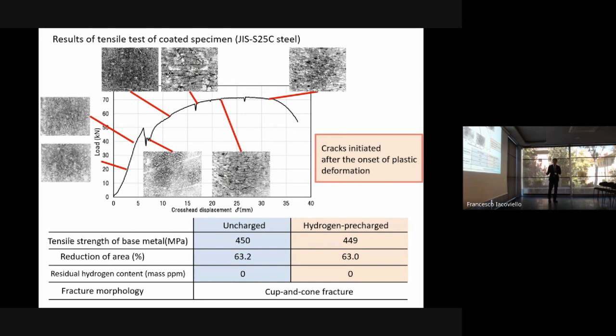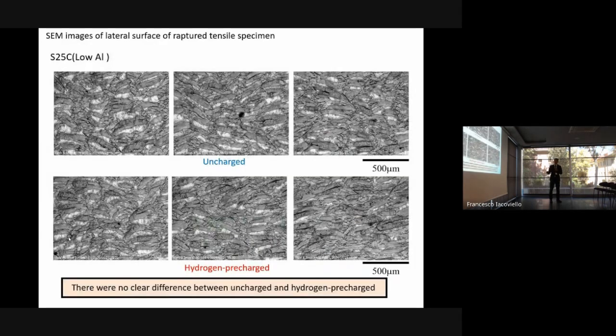These are the tensile strengths of the base metal; the reduction of area and residual hydrogen content are the same in both cases, uncharged and hydrogen precharged. The fracture morphology shows both cup and cone fracture. This is an SEM image of the lateral surface of the ruptured tensile specimen. These are the uncharged one and the hydrogen precharged one.